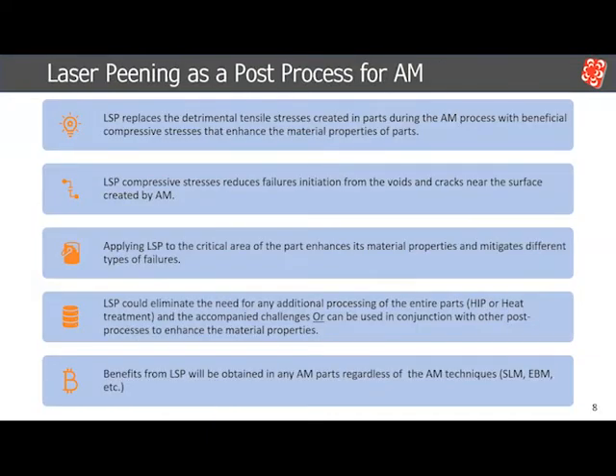So why is laser peening a great post-processing technique for additive manufacturing? The driving force behind the concept lies in the fact that laser peening is actually replacing those detrimental tensile stresses generated from the additive manufacturing process with beneficial compressive stresses that enhance fatigue life. With that, you now have compressive stresses that reduce failures from crack initiation and crack propagation from those voids or pre-existing cracks at or near the surface.